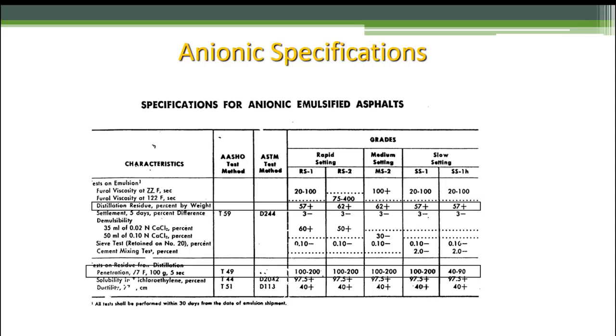Well, understand that sometimes when they shoot that tack, you're shooting a relatively small amount of asphalt on the road. To get it through the spray bar in the distributor truck, they'll dilute it. They'll put more water in, and that'll work. You don't want to leave it in the tank very long when you do that, but you dilute it, put more water in. Now I can spray it out at a higher rate. I keep the pump and the spray bars working at a much higher volume, so I get a more uniform shot rate, or spread rate, I should say.